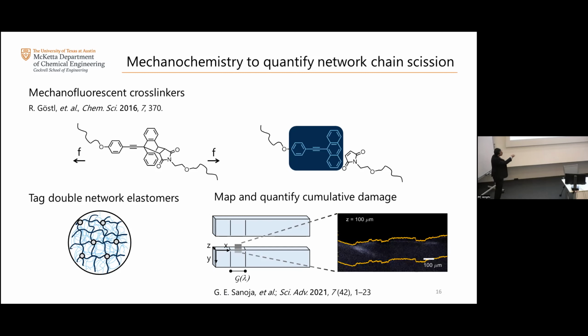So here, what I show in the bottom is an image of one of those images on the confocal microscope that are obtained. And you see, for example, these regions of fluorescence, and this fluorescence right here indicates that you had, for example, a lot of molecular damage. You can see one that is slightly less fluorescent here on the bottom right. And then if you do some nice quantification that I'm going to talk about, you can find your crack edge, and then you can start integrating along the crack edge to actually start getting a metric of how much damage you have.